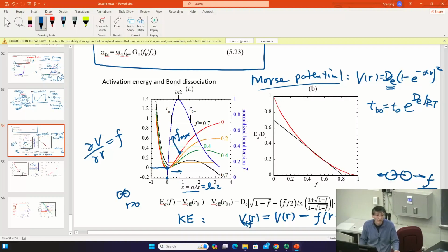For example, if you really have a force reaching a maximum, your bond lifetime instantly goes to that of T0, which is 0.1 picosecond. In our experiment, we can consider that to be instant. So if you apply force as much as F max, your bond will instantly break. What is F max?